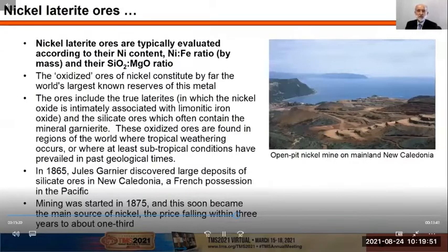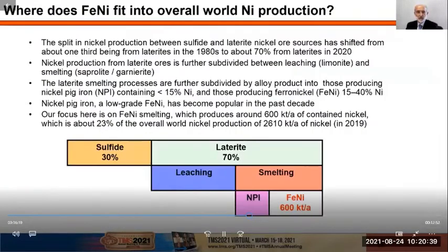Nickel laterite ores are typically evaluated according to their nickel content, nickel to iron ratio by mass, and their silica to magnesia ratios. The oxidized ores of nickel constitute by far the world's largest known reserves of this metal. The ores include the true laterites, in which the nickel oxide is intimately associated with limonitic iron oxide, and the silicate ores, which often contain the mineral garnierite. In 1865, Jules Garnier discovered large deposits of silicate ores in New Caledonia, a French possession in the Pacific. Mining was started in 1875, and this soon became the main source of nickel, the price falling within 3 years to about 1/3. So where does ferronickel fit into overall world nickel production?